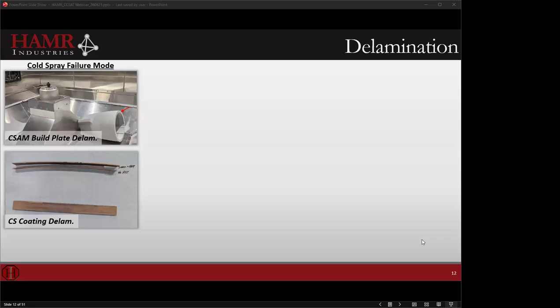Another challenge in cold spray is delamination. I have a couple examples here. We can delaminate from our substrate when we're operating cold spray as a coating approach, and we can delaminate from our build plate. You see an unfortunate delamination here of a relatively large part. So that's both surprising and scary when it happens.